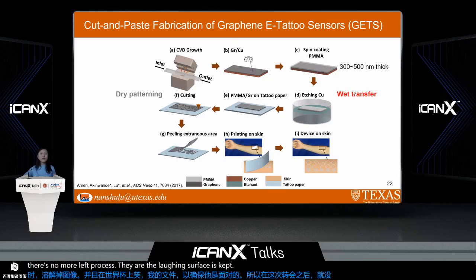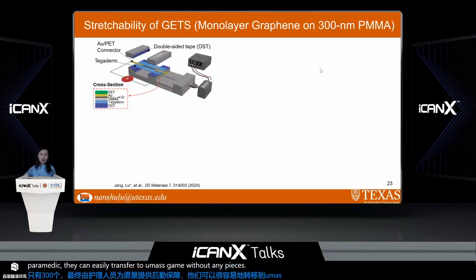And because the graphene e-tattoo is only 300 to 500 nanometer thick, dictated by PMMA thickness, we can easily transfer onto human skin without any adhesive. And we, of course, care a lot about the mechanical reliability of GETs. So we tested the stretchability of a straight GET specimen without serpentine.